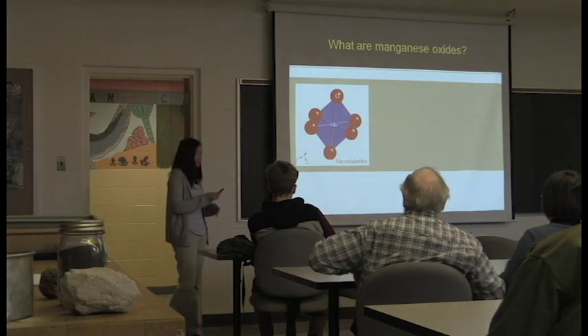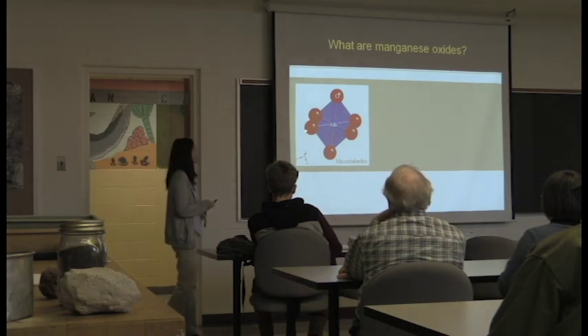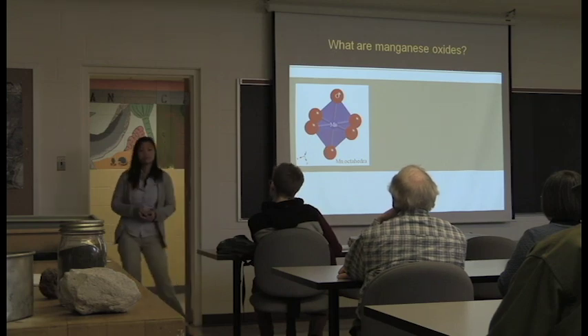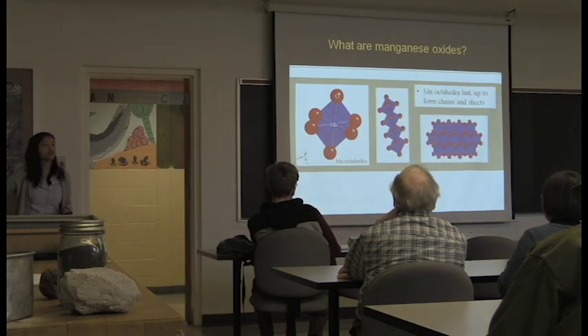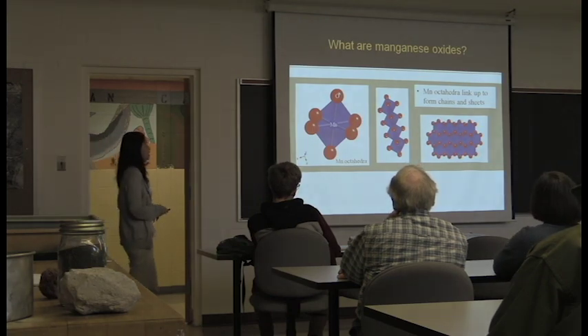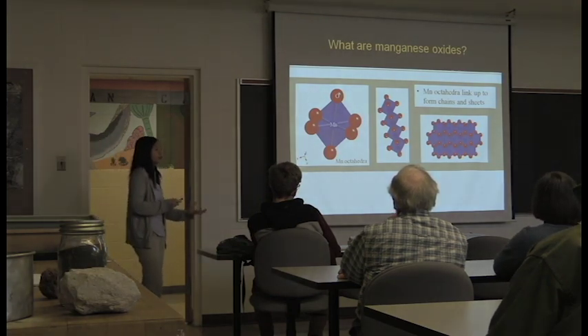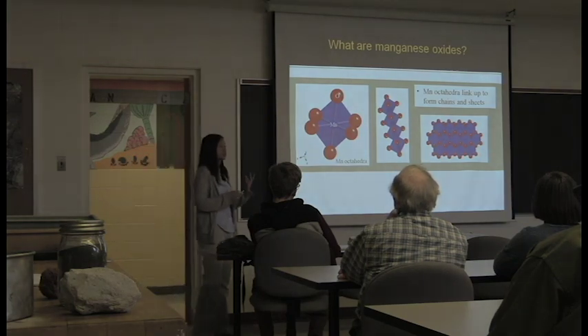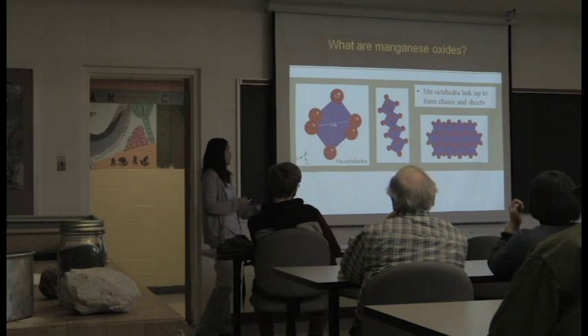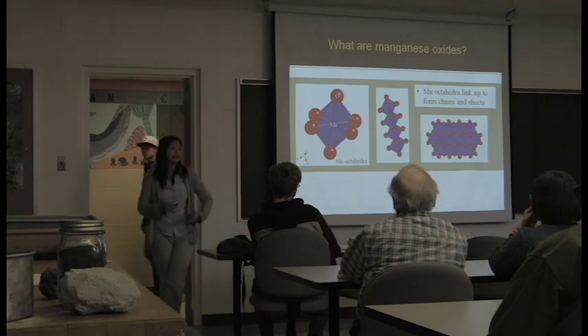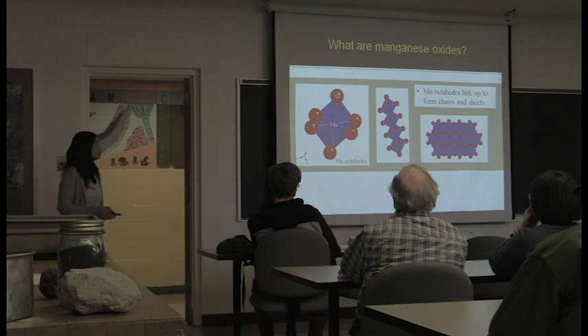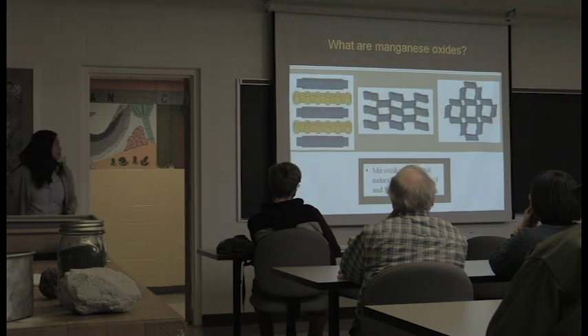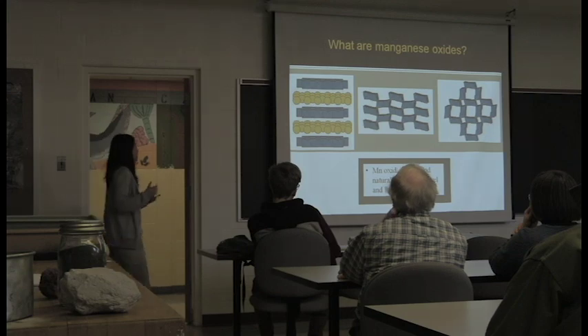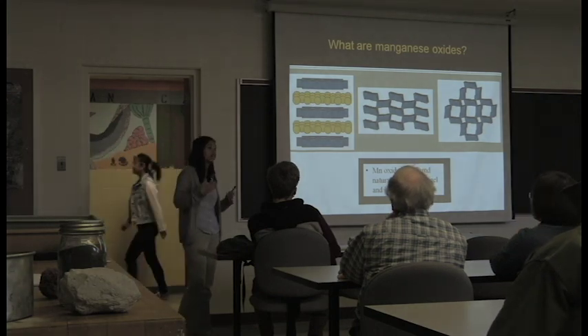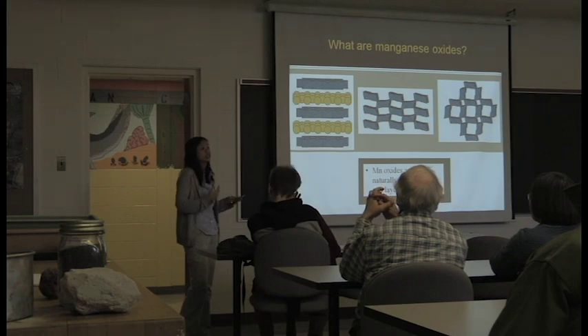The basic building block of a manganese oxide is manganese bonded to 6 oxygen atoms. And so you can link these up to form chains and sheets of manganese octahedra. If you remember in mineralogy, you also have your silicate tetrahedra, which is silica bonded to 4 oxygen atoms, and those can similarly link up into chains and sheets. This is what the manganese octahedra are doing. Once you link those up into chains and sheets, you can also have those chains and sheets combining into a bunch of different manganese oxide minerals.